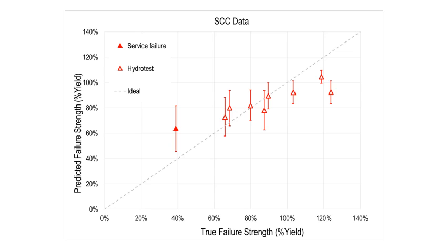Now, what I've decided to do going forward is to say to myself, if I'm concerned with service failures, I'm going to use the more conservative value of 0.84, and that's going to get me a little bit closer to the line. I think it's reasonable to assume that if you have a service failure, it's more likely that that's going to happen when your cracks are at the peak of their crack and shed sequence.